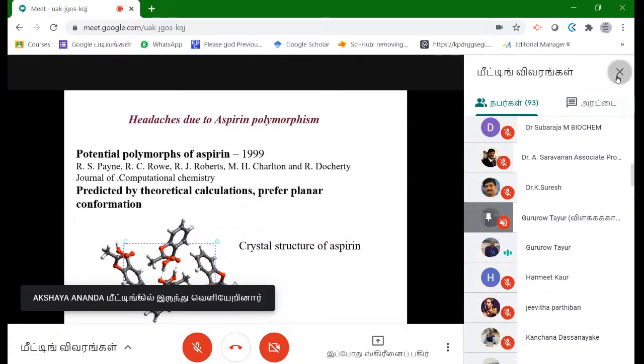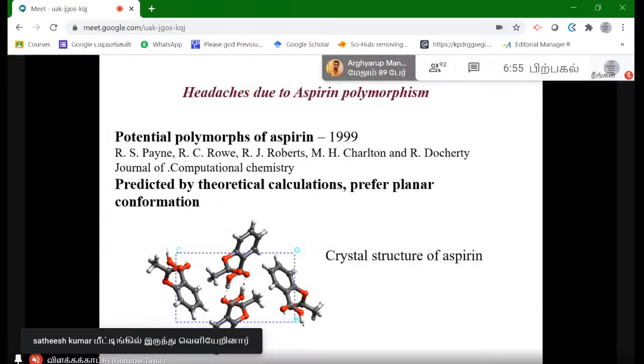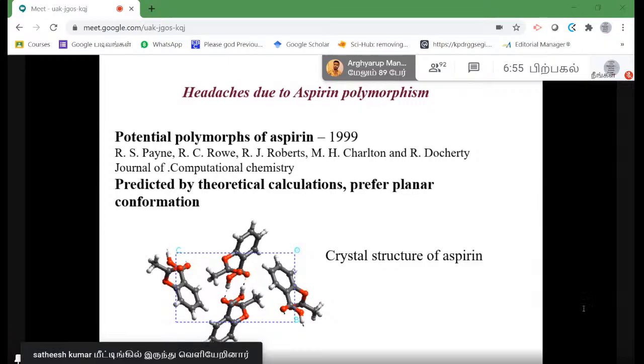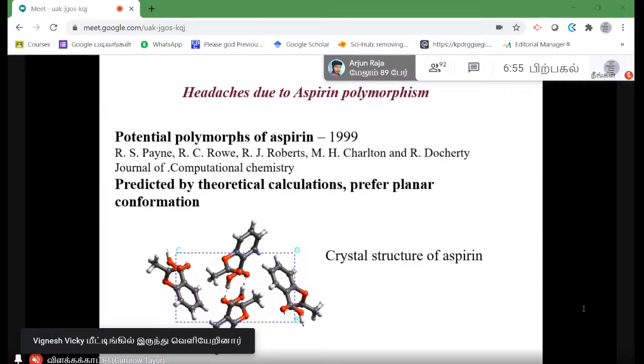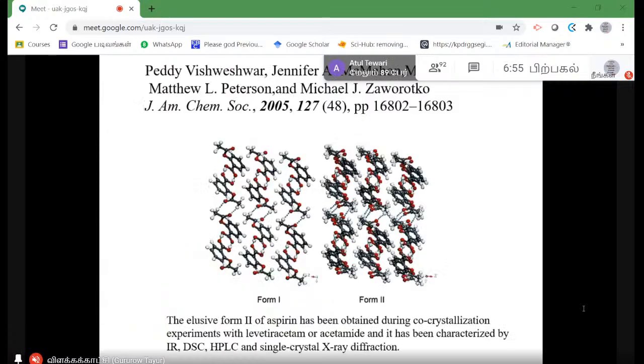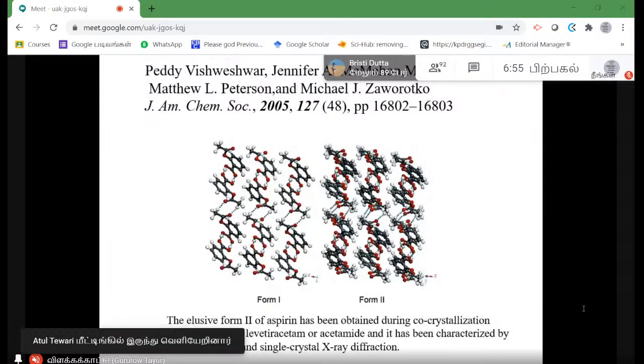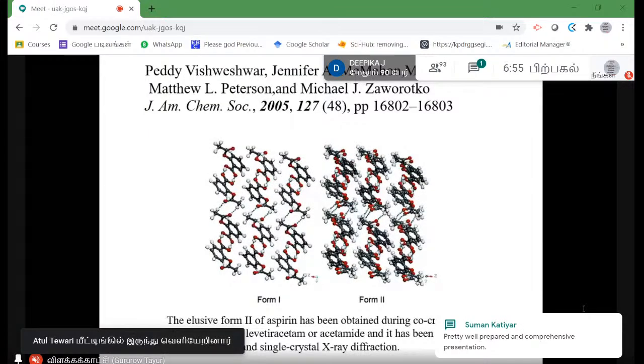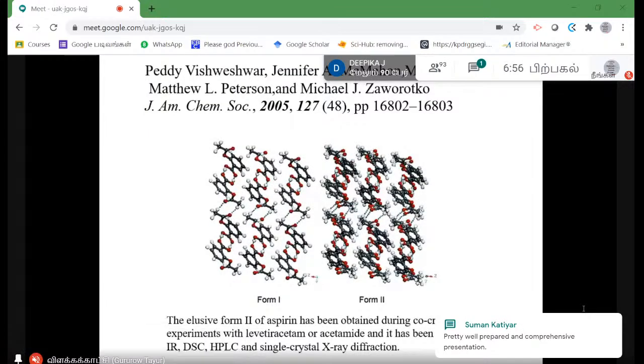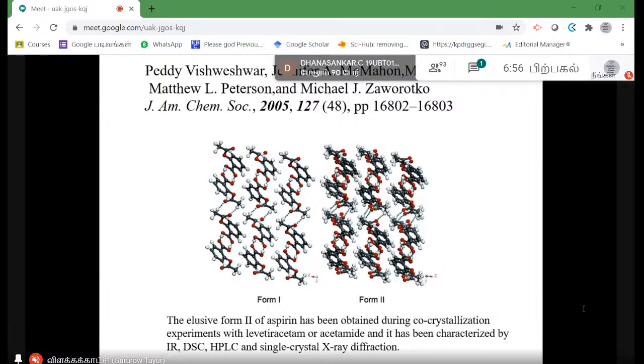When you actually make the crystal structure and determine its structure, the structure of aspirin goes into this crystal form. So people try to make different polymorphic modifications in different solvent media and so on. And a successful venture, which appeared in 2005, was where they were able to crystallize two forms of aspirin. So they wrote: the elusive form 2 of aspirin has been obtained during co-crystallization experiment with levetiracetam or acetamide, and it has been characterized by various methods.